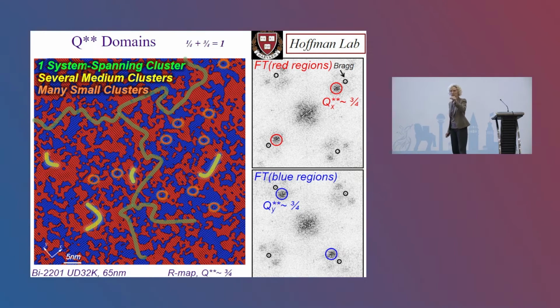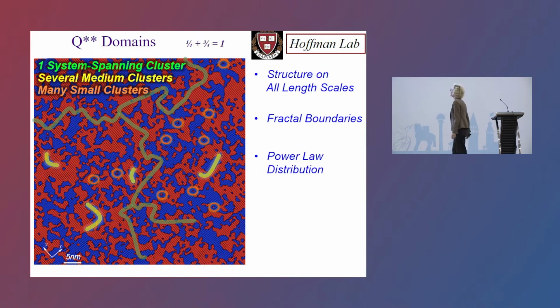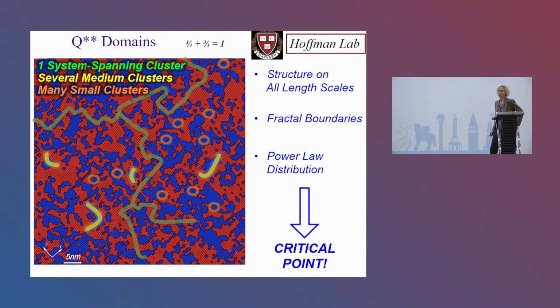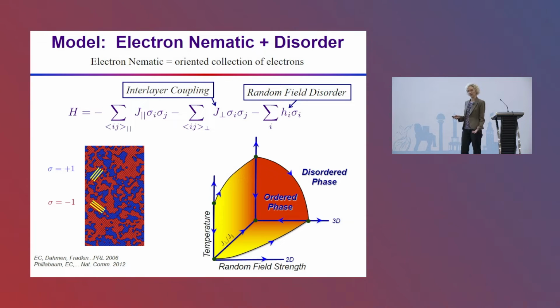And so already you can see a hint that there could be power law behavior in there, because you have structure over multiple length scales and you have a small number of large objects but a large number of small objects. So in fact, there is a power law distribution here. And I'll argue that it indicates proximity to a critical point, that critical behavior is driving this pattern formation. And if critical behavior is driving that pattern formation, we can get critical exponents out of it. Now, to discuss critical exponents, I need a model.